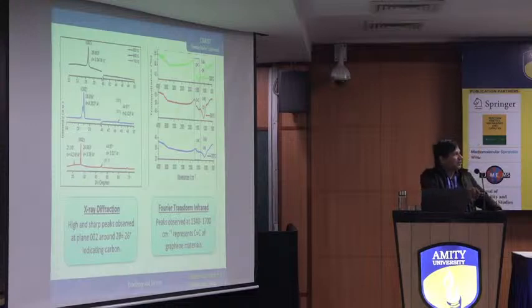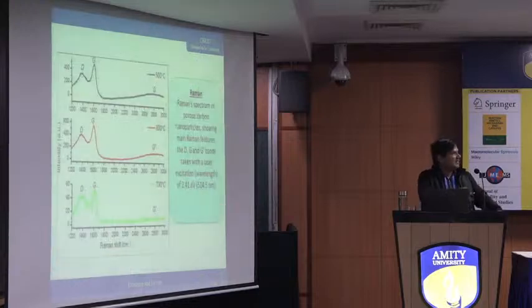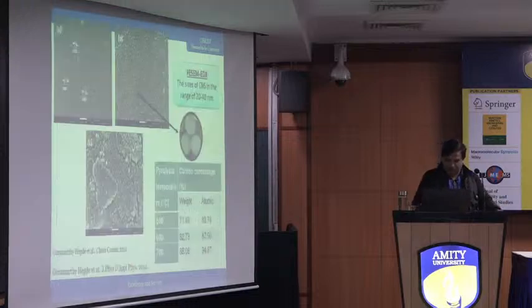And FTIR also suggests the same thing. Now there is no more silicon. It is a C double bond C, which is because of the graphene material, because that's where you are getting the peaks at those points. And Raman again suggests that you have peaks from D, G, G prime, which is for the degeneracy.